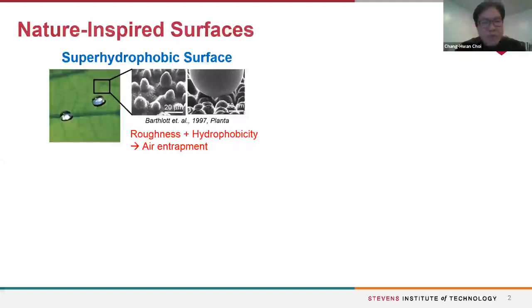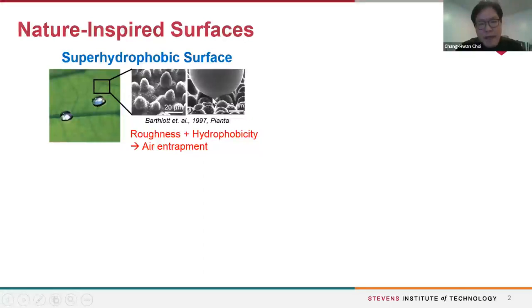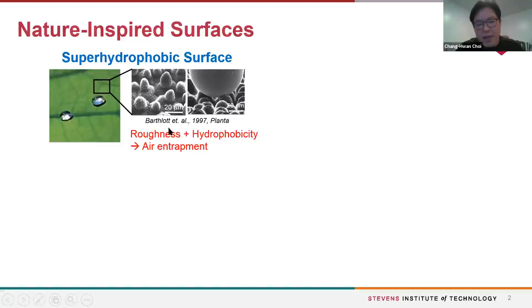The first is super-hydrophobic surfaces. If you look at plant leaves such as lotus leaves, their surfaces are covered with micro- or nano-scale hierarchical structures, and also with hydrophobic wax material. Because of the structural hydrophobicity, a liquid droplet doesn't wet the surface. Instead, an air or gas layer is trapped within the structure, so the liquid has minimized contact with the solid surface and very slippery behavior — it can easily roll off if the surface is tilted. The key is to combine physical roughness with surface hydrophobicity to trap air between structures and minimize liquid–solid contact.